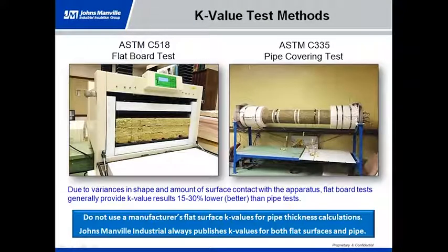Now, how we test these materials is pretty simple in concept, a little bit more complicated in reality. We're talking about the difference between a flat test versus a round pipe covering test. On the left-hand side, you'll see ASTM C518, which is the flat test. Because K values are a thermal property, we can measure that performance quite easily.